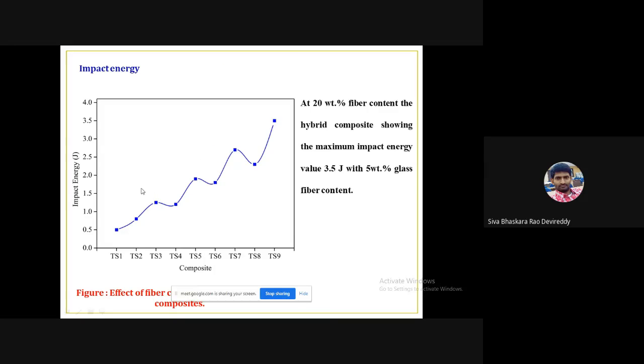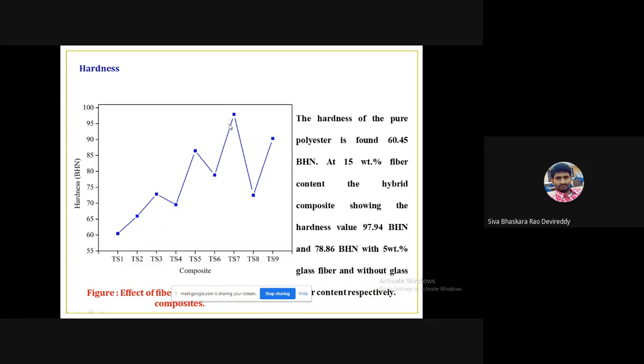Impact energy gradually increases with respect to the fiber loading. The maximum impact energy is found to be 3.5 joules. Similarly, the Brinell hardness also increases. The maximum hardness is found to be 97.94 Brinell hardness number at 15 wt.% of broom grass root and 5 wt.% of glass fiber.